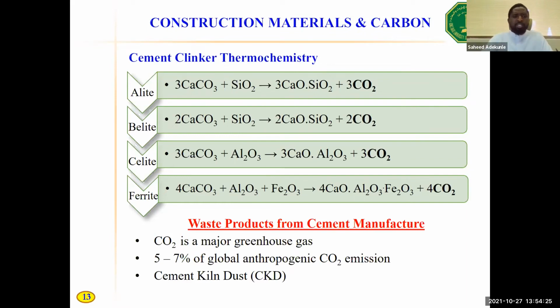And we know that CO2 is a major greenhouse gas, as we showed on the previous slide. It follows that we are not going to look into the energy consumption of cement manufacture alone. We look into the CO2 itself as a product of cement manufacture. When combined together, it has been estimated that every ton of cement manufactured results in approximately 800 kg of CO2. In fact, some analysts would prefer to say it's a one-to-one ratio.